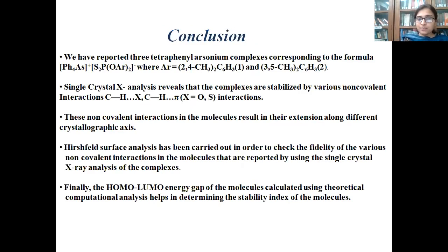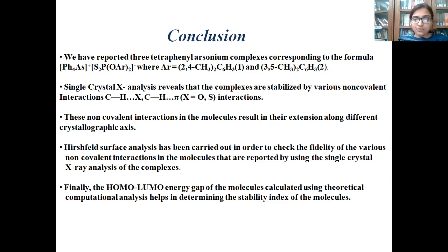In conclusion, we have reported tetraphenyl arsonium complexes corresponding to the formula [Ph4As][S2P(OAr)2], where single crystal analysis reveals that the complexes are stabilized by various non-covalent interactions — C-H···X and C-H···pi. These interactions result in extension of the molecular structure along different crystallographic axes. Hirshfeld surface analysis was carried out to verify the fidelity of the non-covalent interactions reported by single crystal X-ray analysis. Finally, the HOMO-LUMO energy gap calculated using theoretical computational analysis helps in determining the stability index of the molecules. Thanks.